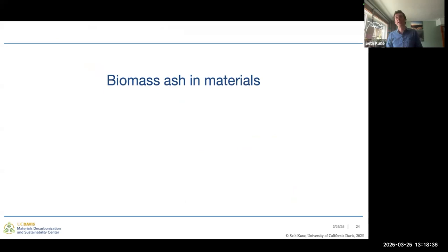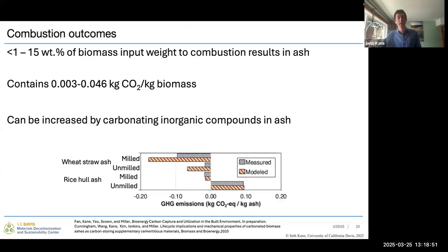Okay, so I'm going to start by talking about the combustion product of ash, different ways that we can use that. This is going to be a pathway that prioritizes energy production. So we don't necessarily expect huge benefits from the material itself. It's sort of just a byproduct of that energy generation. And typically from that, we're getting about 1 to 15 weight% of that original biomass input. And this contains very little carbon because it's mostly those inorganic compounds that are present in the biomass.